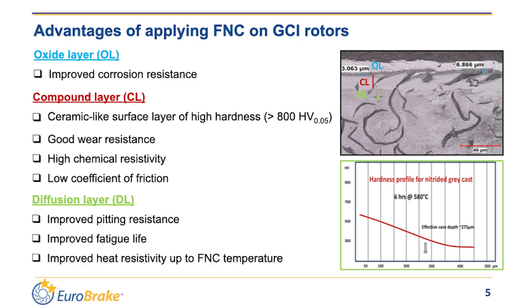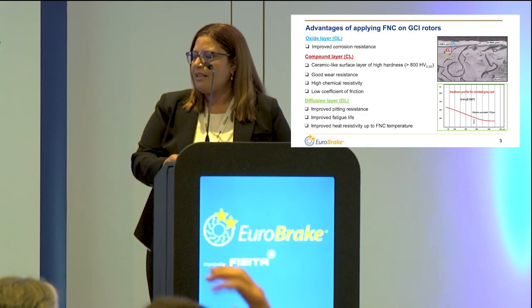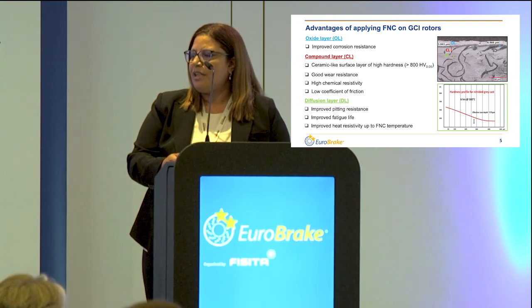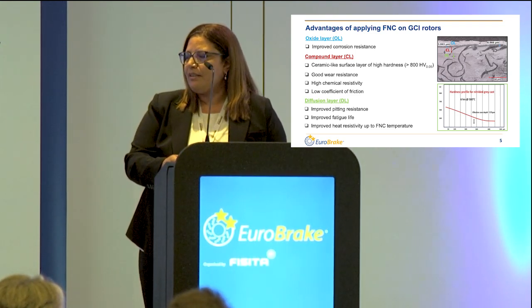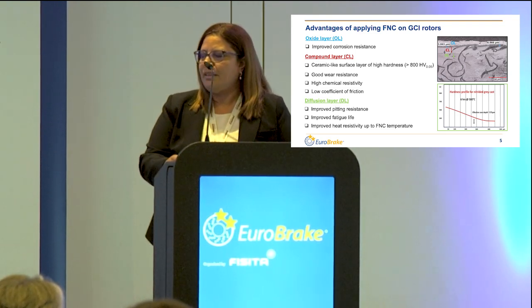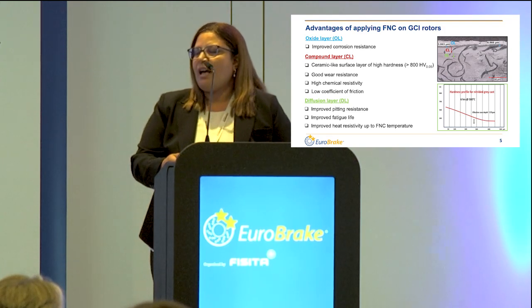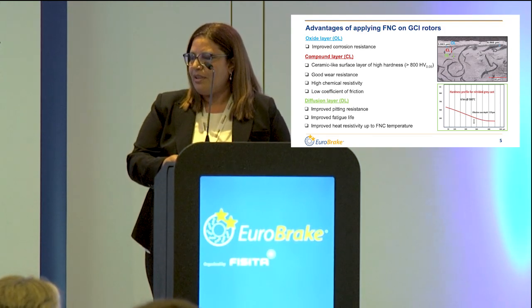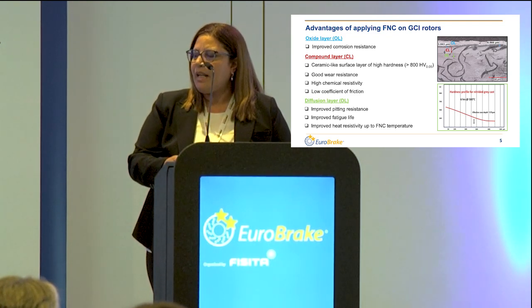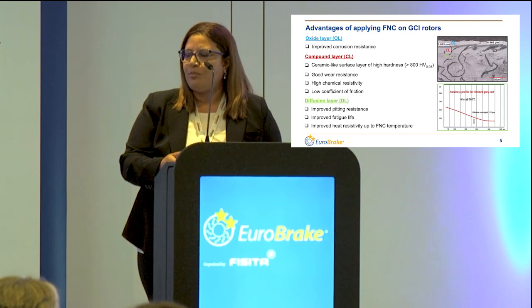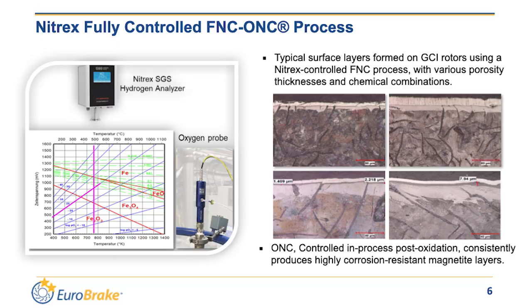During the treatment, it forms a compound layer that is composed of epsilon and gamma prime, and underneath it forms a diffusion layer that is composed of alloying elements, nitride and carbide, and it can achieve up to 275 microns as an effective case depth. And on top of the compound layer, we can apply an oxide layer that will improve the corrosion resistance. FNC is gaining popularity.